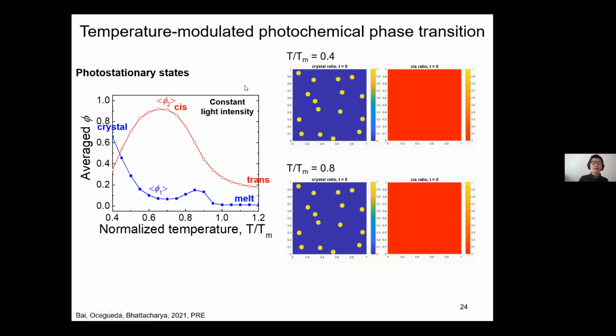So I call it temperature modulated photochemical phase transition. So you can basically use temperature to control your actuation of the material. So indeed, this is some simulation. I just show some interesting result.